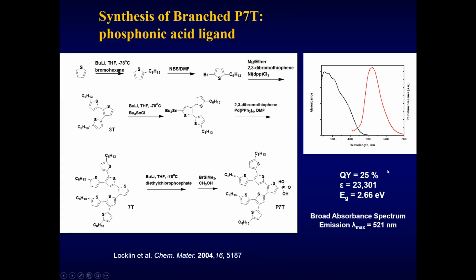Now, again, unfortunately, I will not be able to show AFM pictures here simply because we were not able to isolate it in the first place, but what we try to highlight here is that aggregation and stacking can also be observed indirectly by looking at their energy transfer properties.